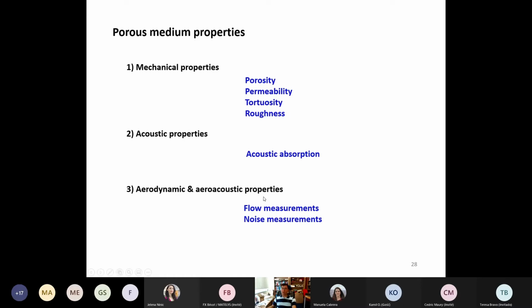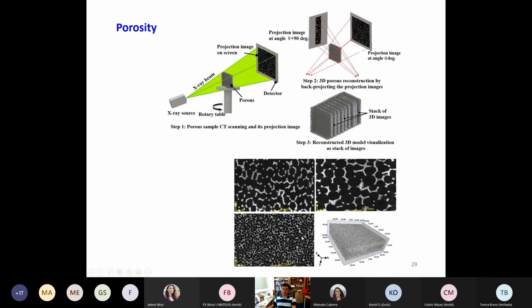On the aerodynamic and aeroacoustic side, we do need to measure the flow and understand how the flow interacts with the porous material, and also noise measurements in the near field and far field. So in terms of porosity, the way that we measure, we have tried all sorts of methods, from dipping the porous material inside water and then trying to measure the rise in water. But the best method that we have used so far is CT scanning.